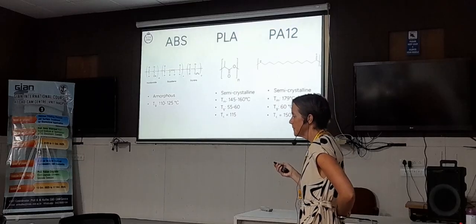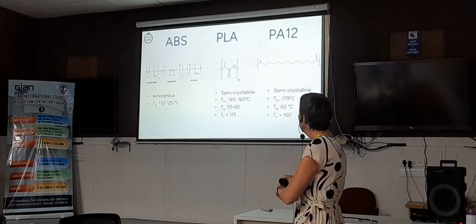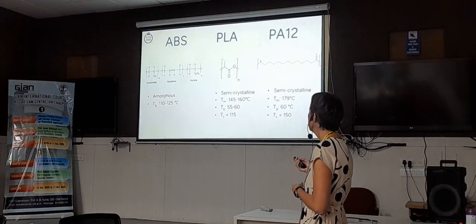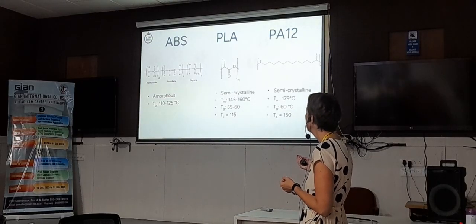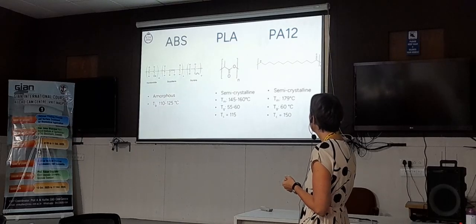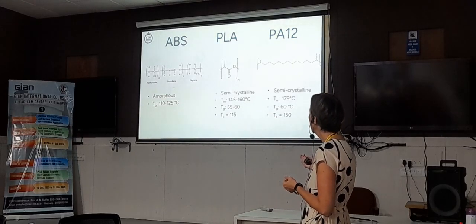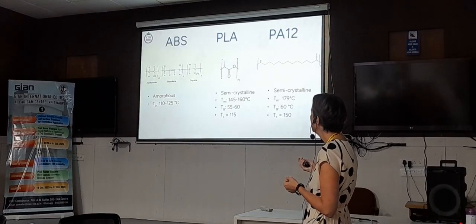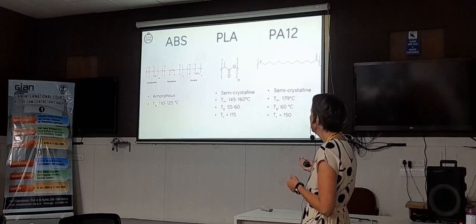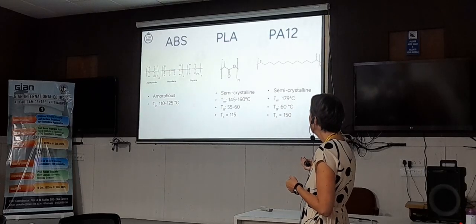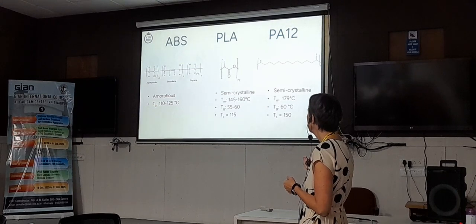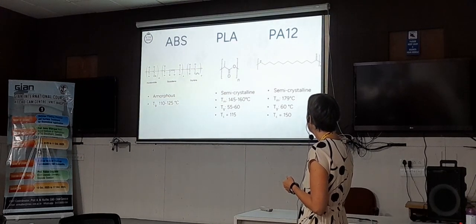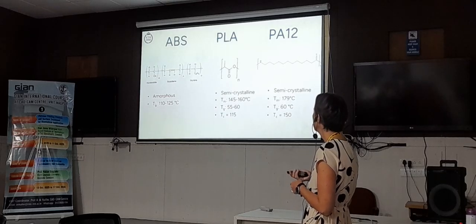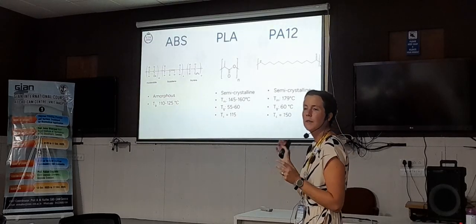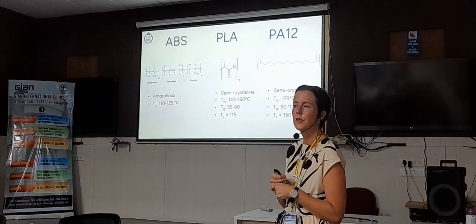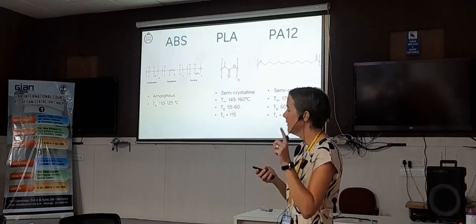And I just showed a few examples of polymers that are normally used in 3D printing: ABS, polylactide (PLA), and PA. And how the Tg varies. In ABS you have the Tg between 110 and 125, PLA has around 55 to 60, and the PA is 60. And also that the melting point varies. So we need to have these values in order to start printing. And the degradation, when it starts to degrade.